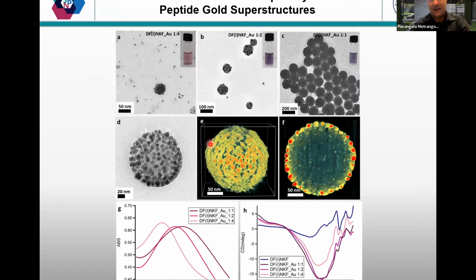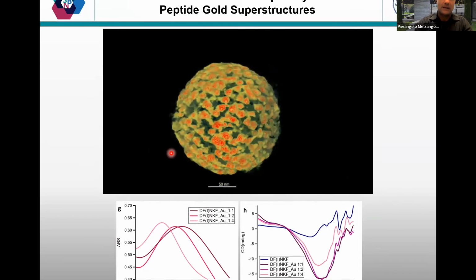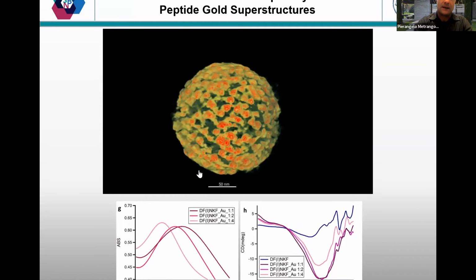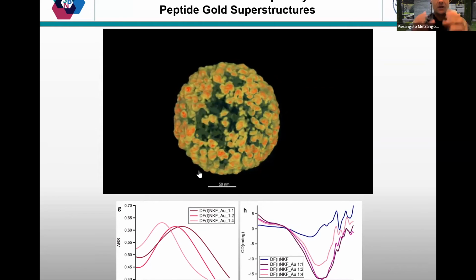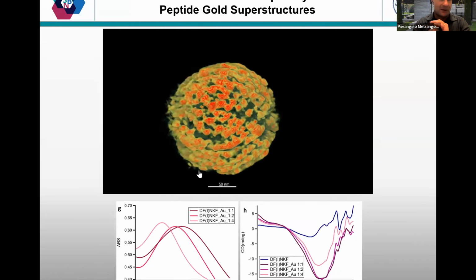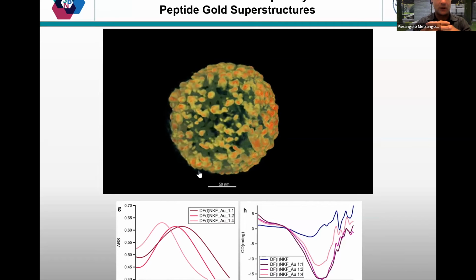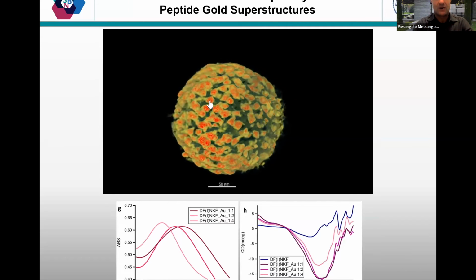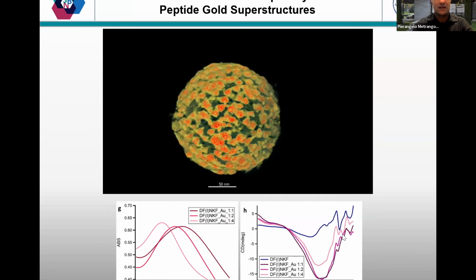Surprisingly, these very complex objects just self-assemble in solution. You mix the two compounds in water, warm it up to 60 degrees for half an hour, and what you get are these very beautiful objects, where inside there is the peptide. There is a video again here, and you can see the 3D reconstruction. Inside, there is only organic matter. Outside, this self-decorates with gold nanoparticles, and since the gold nanoparticles are on top of a chiral peptide, you can see a chiroptical signal in the visible light.